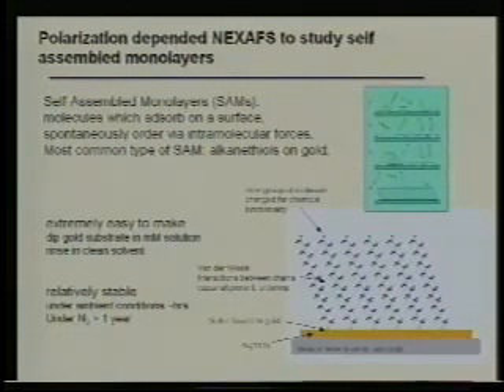But as it turns out, the van der Waals interaction is such that it will cause these alkane thiol groups to repel one another. Yet the activation energy for the thiol to bond to the gold is such that it's more energetically favorable for these materials to stand up, so they actually self-assemble in real time. So if you wait for some period of time, depending on preparation conditions, these things will all stand up.